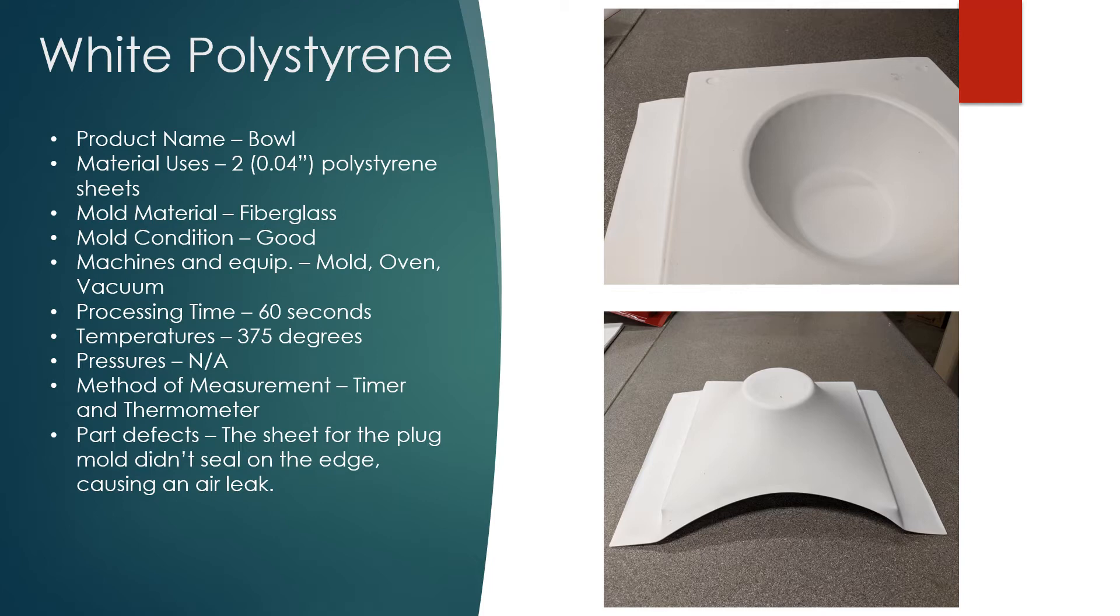The part defect for white polystyrene is on the plug mold, the bottom picture. The edge that's closest to us, or closest to you if you're facing your laptop screen, it didn't seal properly so there was an air leak. That's why it didn't really take shape.